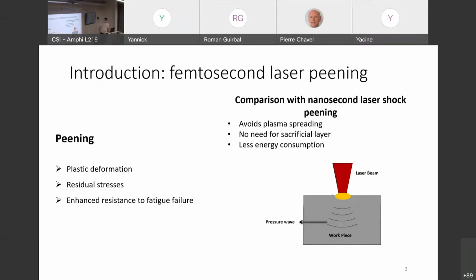For a few years now, many people do laser peening, mostly with nanosecond lasers. Here the project is to do comparable work with a femtosecond laser. So peening is a technique which consists in putting a laser beam on a material, creating a pressure wave, which creates inhomogeneous plastic deformation in the material. And as a consequence, there are some residual stresses created after this shock. And those residual stresses can enhance the resistance to fatigue failure of the material.